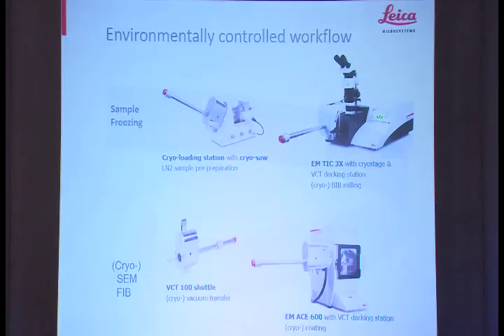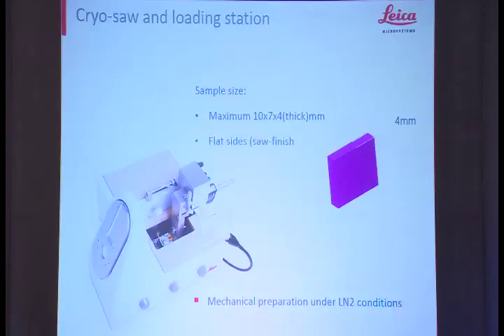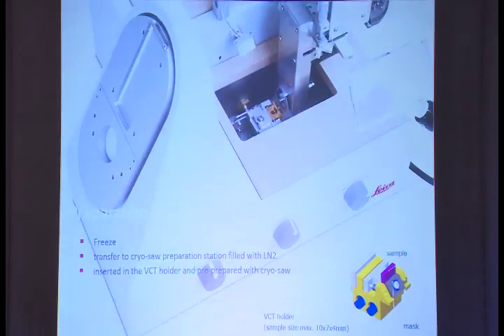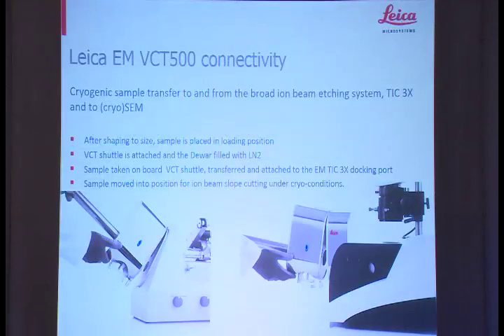So we developed a cryo saw. Once we've frozen the sample, it is frozen between two metal planchettes. So we'd need to cut through the metal and the sample to remove most of it so we can get at the sample itself. So we developed a cryo saw which helped us to cut through the sample and through the planchette to hold it with a little mask here, and therefore allowing us to have a sample just sitting above a mask as shown in the previous diagram, so we can just bombard it with argon ions to flatten the surface. So we did this, and we managed to get the sample into the TIC.